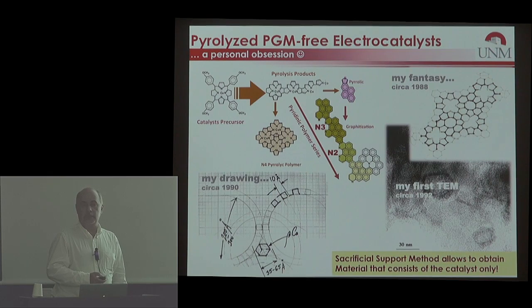Why is making the catalyst still an art and not a science? Because you need to advance towards almost full graphitization of the material, but you need not let your nitrogen get incorporated as a graphitic nitrogen. So you need to arrest the process of graphitization of the carbon-nitrogen system just before you get your nitrogen to be entirely diluted into the graphene sheet. So you need to retain nitrogen in some sort of form available for further coordination, mostly associated with defects. Whether on the edge or in plane, it's again a scholastic discussion.